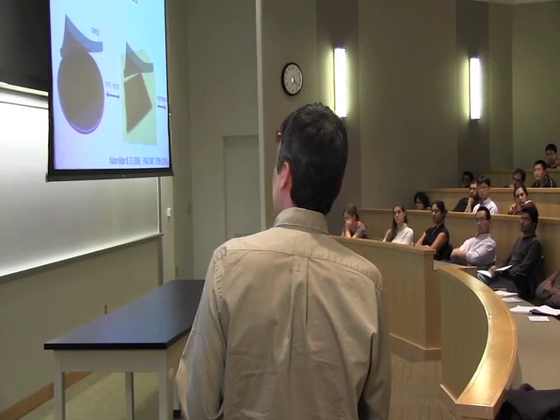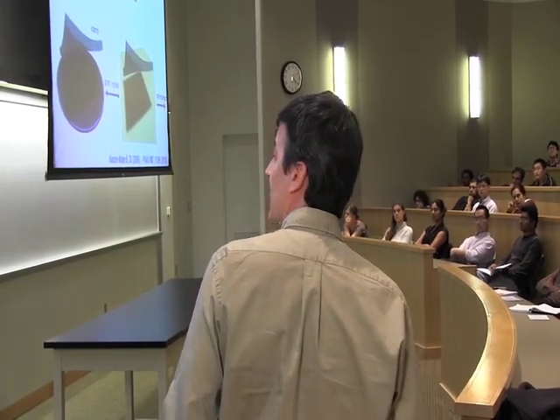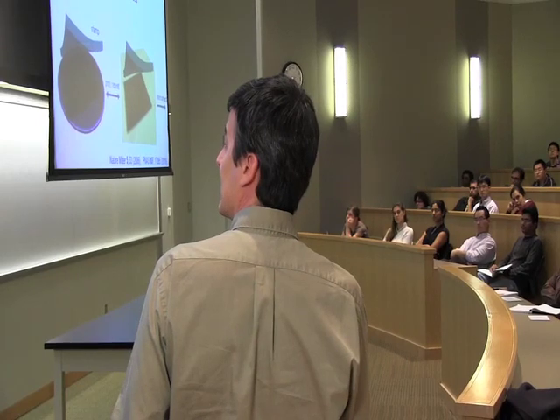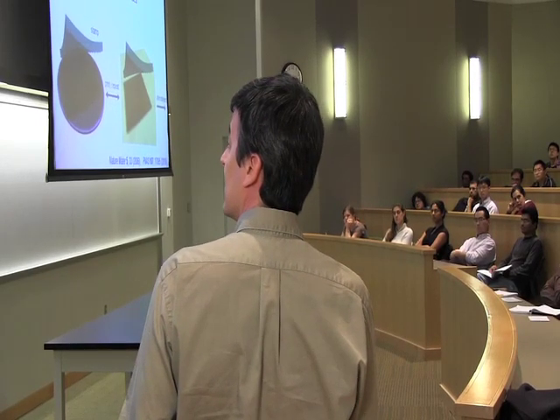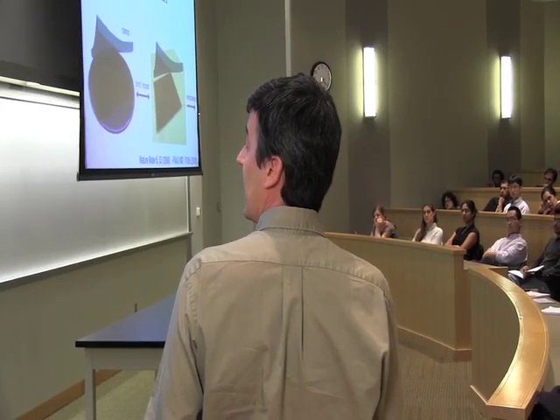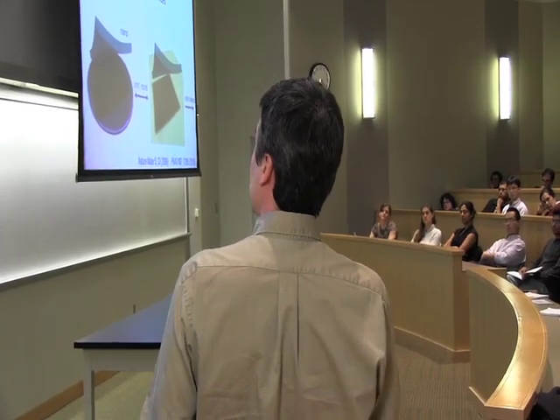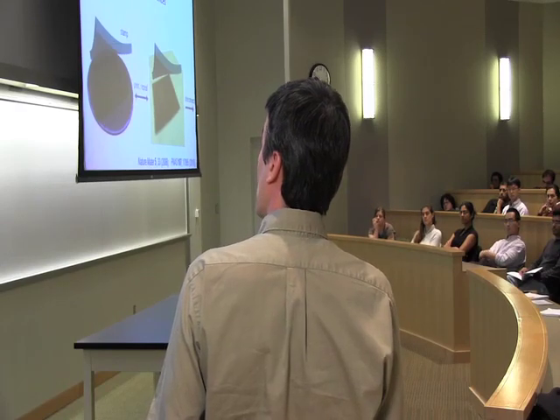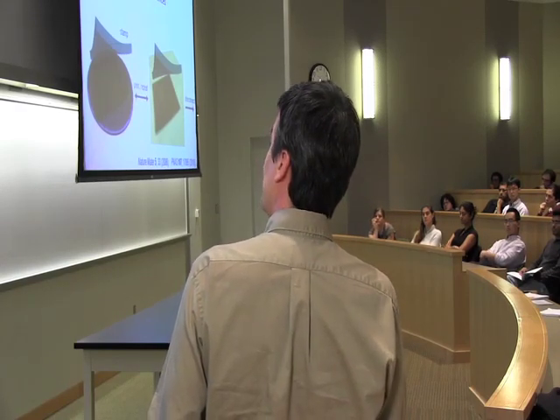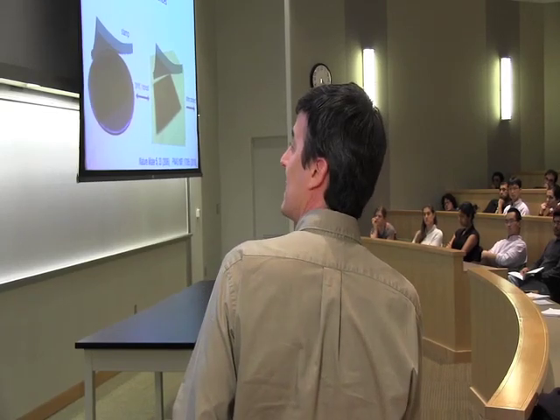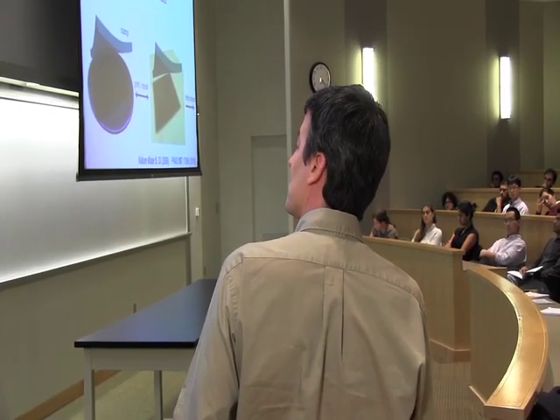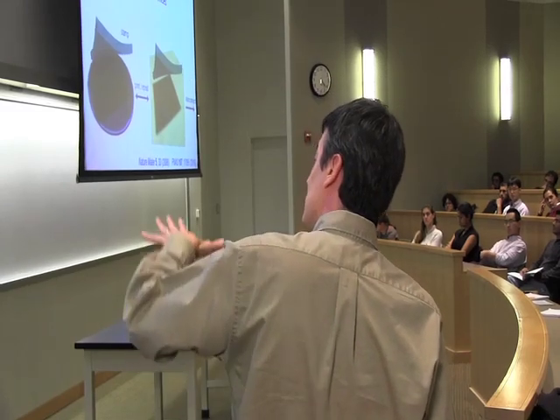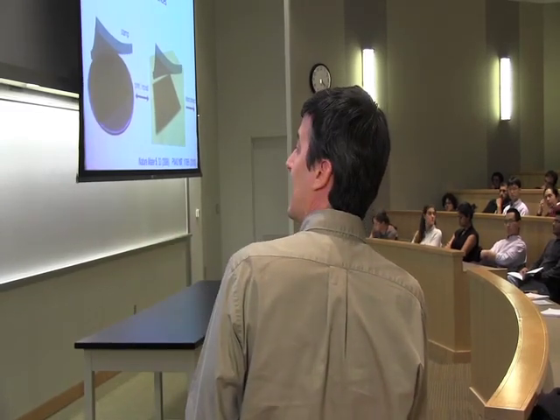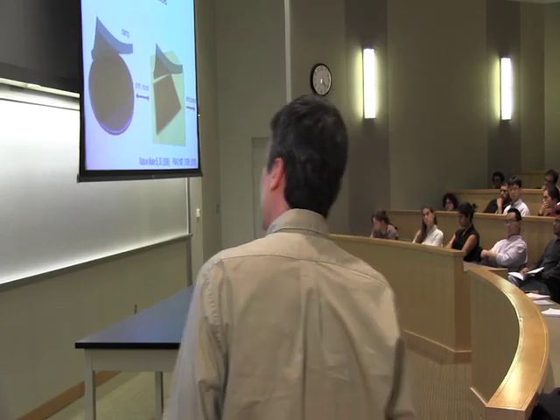It really has to do, again, with the physics of soft adhesion. And I won't step you through the different strategies. One way is to exploit the viscoelastic nature of the elastomer. It turns out that because of the viscoelasticity, the interface adhesion can be strong at high peel rates and, by comparison, low at low peel rates. So you can peel quickly to ink, you peel slowly to print. That would be one example. There are other ways to add texture and relief onto the stamp surface using principles of gecko adhesive so that you can control with pressure the contact areas, allowing you again to go from strong to weak adhesion. So I won't go through those details in this talk, but just make the point that that can work at high yields.